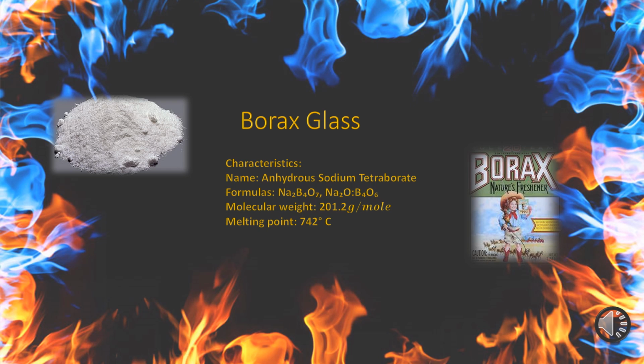Once the borax has been turned into the fused anhydrous tetraborate, it must be kept in airtight containers, as it will start to absorb moisture, and moisture is not what you want during the melting process. Borax is used in almost every crucible fusion. Due to its lower melting point, the slag formation temperature is also lowered, which facilitates the slagging of the sample. It is also an excellent solvent during the fusion process.